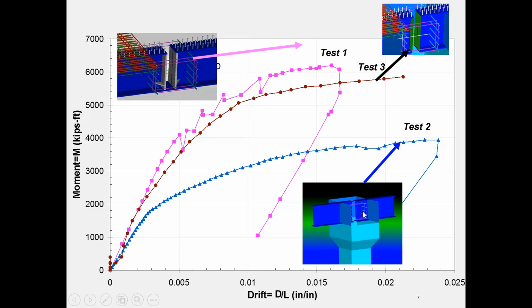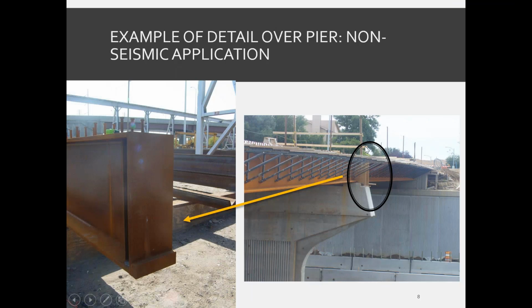If you don't, for example, here is a one test specimen that we didn't have any end treatment. So there was no end plate. There was no mechanism to transfer the compression from one girder to another girder. And as a result, the bottom flange crushed the concrete and the capacity of the specimen dropped by 50%. So this is the most important thing that you need to follow. Now, one detail that we have used on many projects, by the way, there is many of these bridges in service right now. They have exhibited very nice behavior.